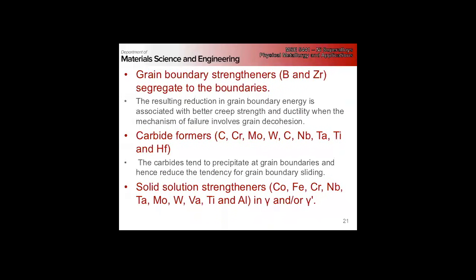The grain boundary strengtheners - the key ones are boron and zirconium - segregate to the boundaries. They reduce the grain boundary energy, giving us better creep strength and ductility. Remember, anytime we lower the energy of an interface, we reduce its mobility - we make it more stable.